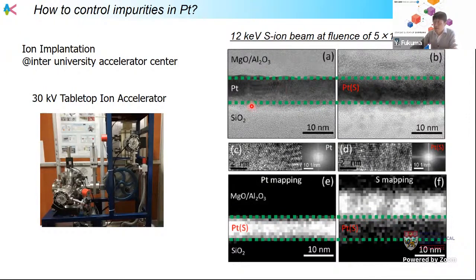So we deposit the platinum layer on a silicon wafer with an oxide layer. Then we also put an MgO capping layer, and also an aluminum oxide capping layer, to decrease the damage of the ion implantation. Then this is the platinum layer with ion implantation of sulfur ions.